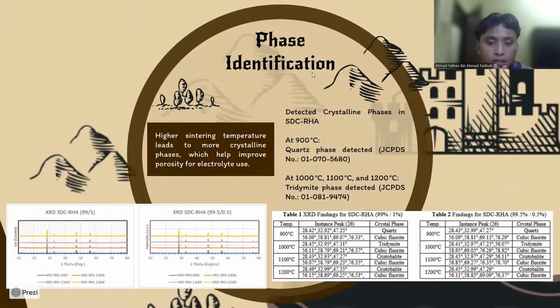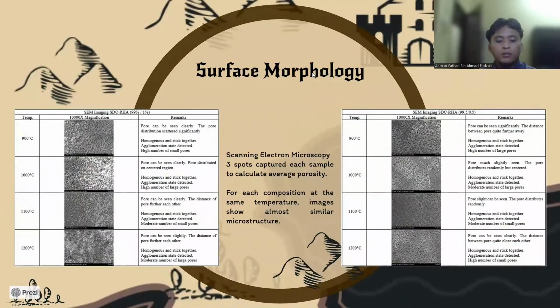For XRD, here's what XRD reveals. At 900 Celsius, as we can see, quartz phase is detected. At 1000, 1100, and 1200, there is tridymite and also cristobalite phase. For SEM, the same images reveal that each sample was taken at 3 different spots. For each composition at the same temperature, the images show almost similar microstructure. There are a lot of white spots and black spots.